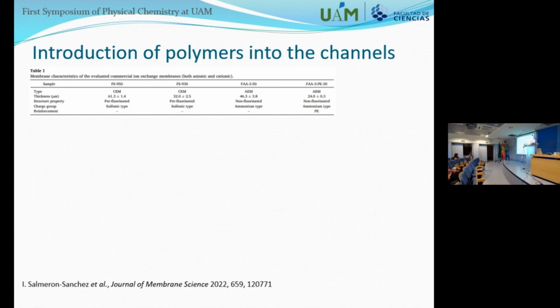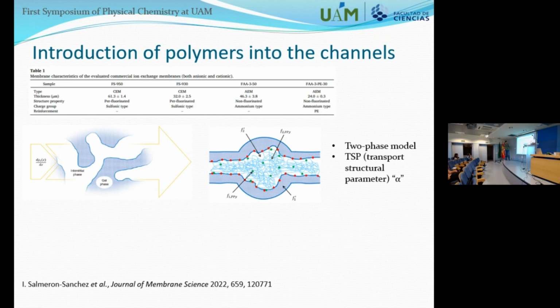So it was done here with 4 membranes, 2 cation exchange membranes and 2 anion exchange membranes. The polypyrrole was introduced in the membrane and it was polymerized in situ. And so we fill the ionic channels with some polypyrrole structure. And for that, in order to study what the conduction mechanism of the ions is, since it's not very clear, they use a 2-phase model that was available in the literature, but it was implemented for this case, and it was also improved in order to explain the results obtained.